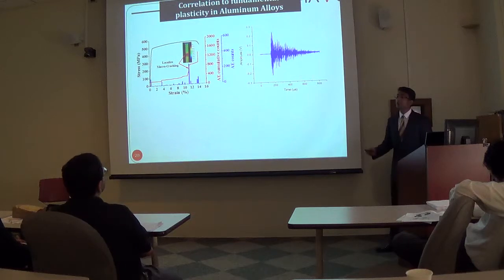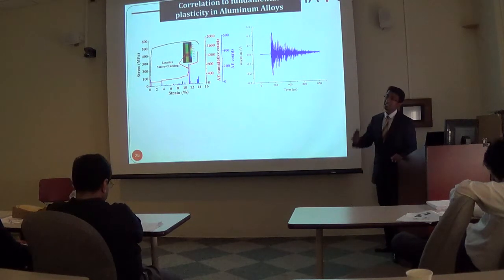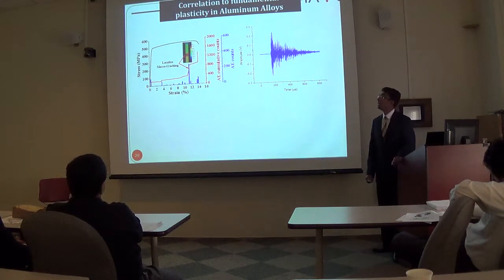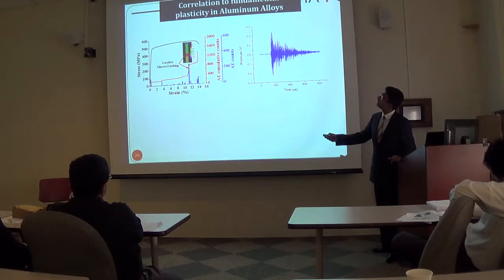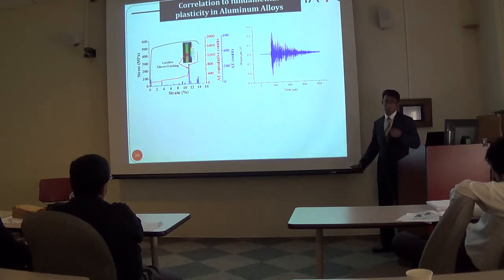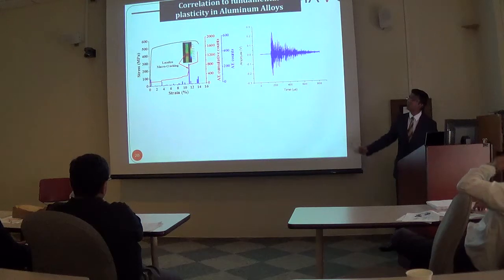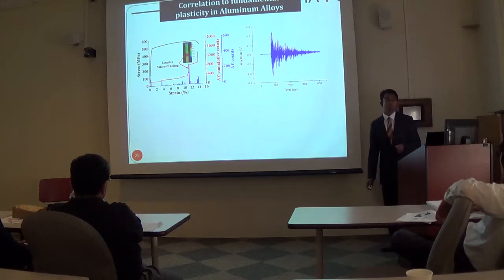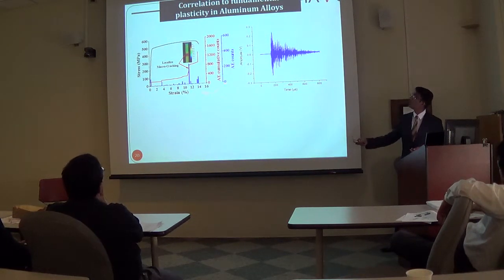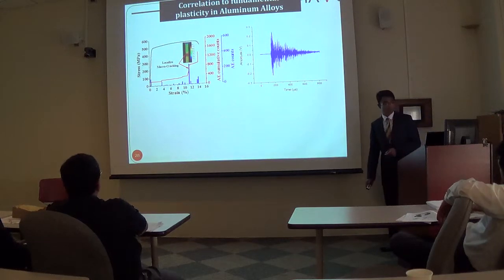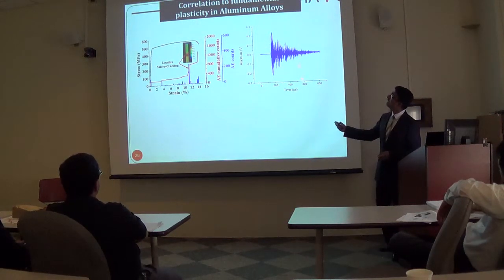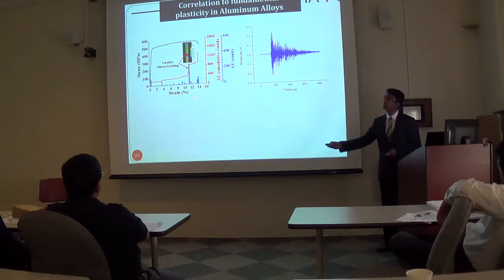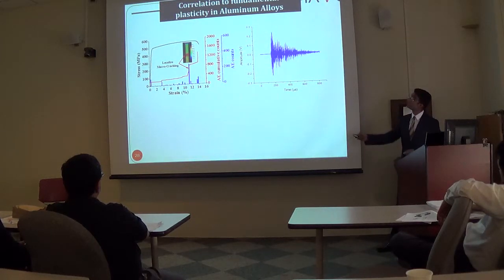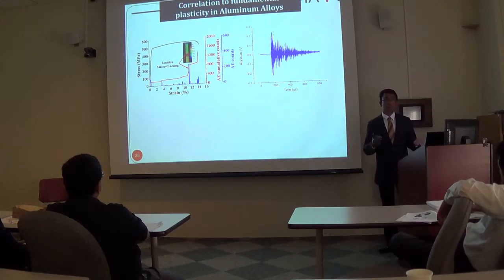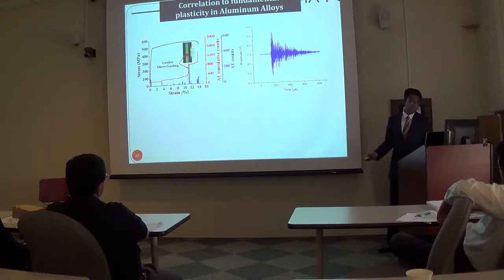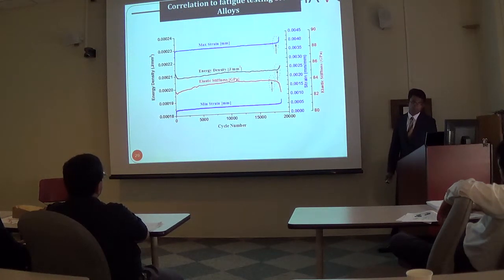Now, the DIC was then utilized to help us understand exactly the onset of the cracking in the aluminum alloy. And as you can see here, as the strain maps increase and the crack started to initiate, you can see a jump in the AE counts that was picked up, both in the AE cumulative counts and in the instantaneous counts. And this was then utilized to understand the AE waveforms that were associated exactly with this region. It was seen that the AE waveforms associated with the cracking were very similar to the yielding, but had a much higher amplitude and showed a burst of emissions.